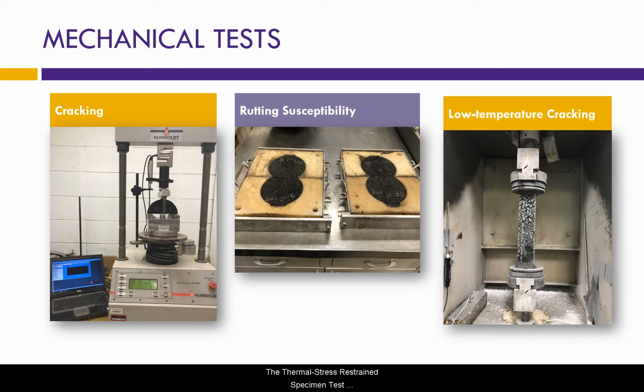The thermal stress-restrained specimen test was used to determine the tensile strength and temperature at fracture. The prepared beams were attached to the machine and placed in an environmental chamber for conditioning. A tensile load of 50 Newton was applied to the sample while cooling the sample at a rate of 10 degrees per hour. Cooling was continued until fracture failure of the samples was observed.